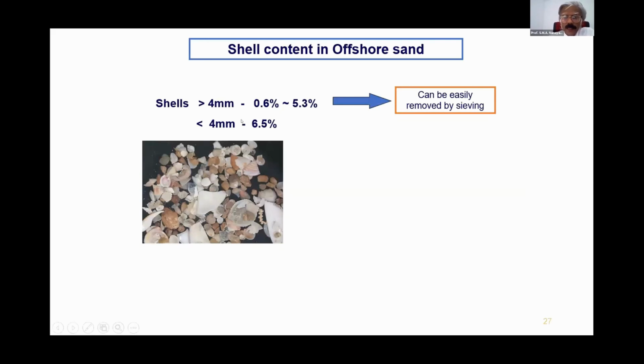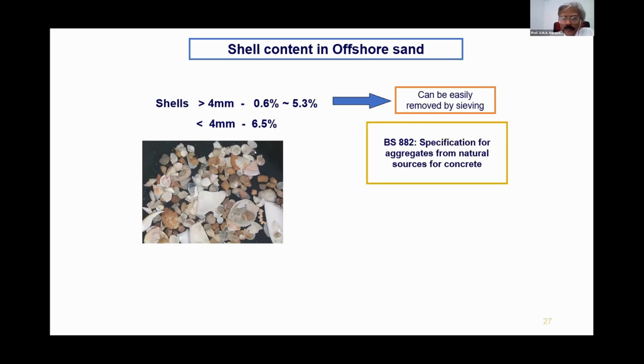We can easily remove the shells greater than 4 millimeters. Now, sand is defined as the particles less than 4 millimeters. So we have to remove the particles more than 4 millimeters, and you can easily remove the particles greater than 4 millimeters. So it contains shells and pebbles. Now, less than 4 millimeters, it is difficult to remove the shell fragments.